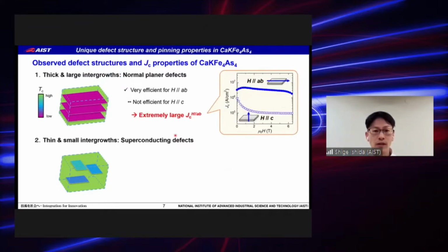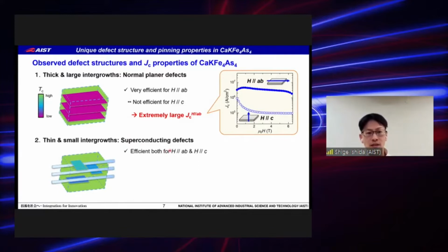Therefore, we consider that these defects are responsible for the extremely large JC with field along the AB plane, and the resultant large anisotropy against the magnetic field direction. Then for the other one, the thin and small intergrowths, they are thought to be efficient for both magnetic field along the AB plane and the C-axis.